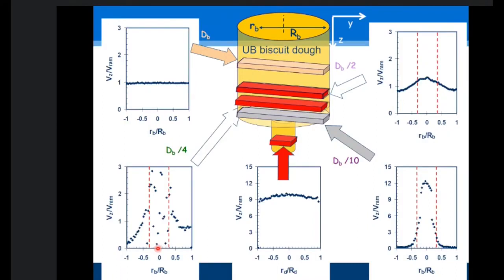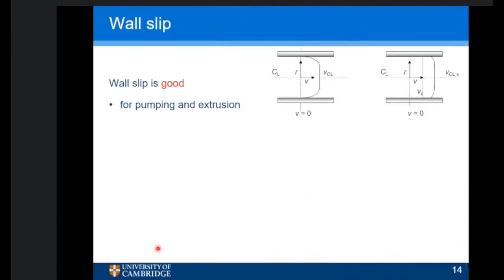So these pastes do slip. It's good for pumping and extrusion because it means everything moves through as a plug. So the limiting case is where your wall shear stress for your slip is less than the yield stress of the material, and everything just moves. Once you get it to change shape, it flows through quite nicely.